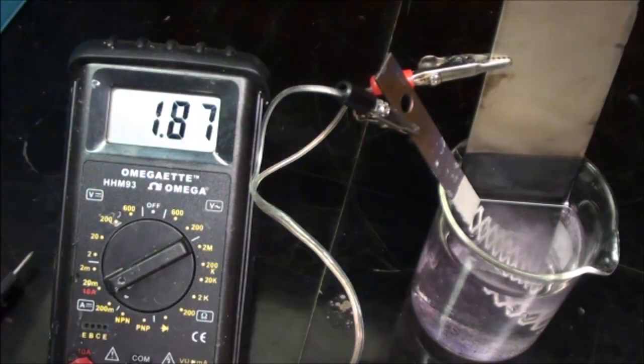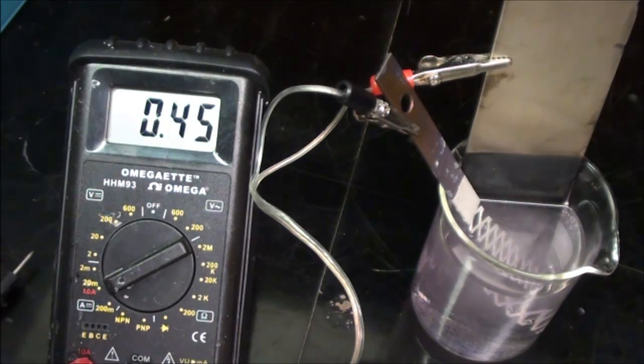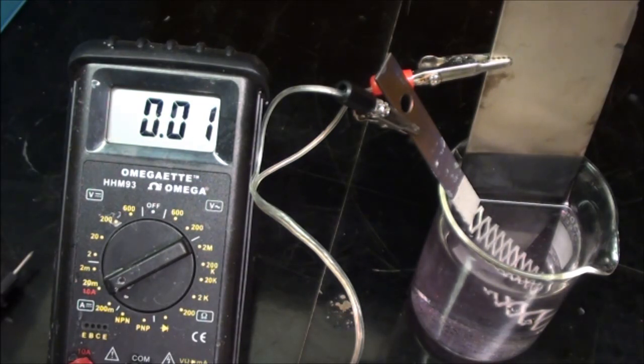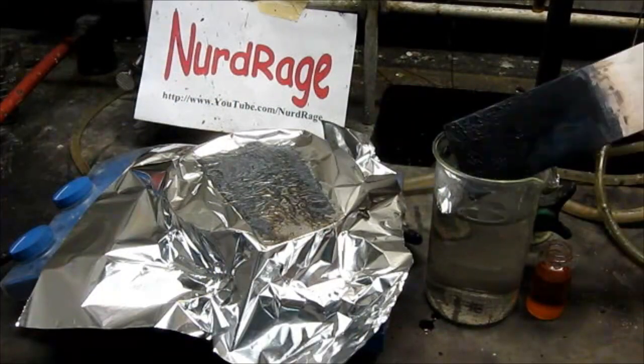Now you might be thinking, why don't we apply the manganese nitrate to the titanium directly and skip the cobalt layer? This is because the manganese dioxide is highly oxidizing and will actually directly oxidize the titanium, forming a passivation layer of titanium dioxide between the manganese dioxide and titanium. Having cobalt in between the two layers avoids this. And here we have our manganese dioxide electrode.